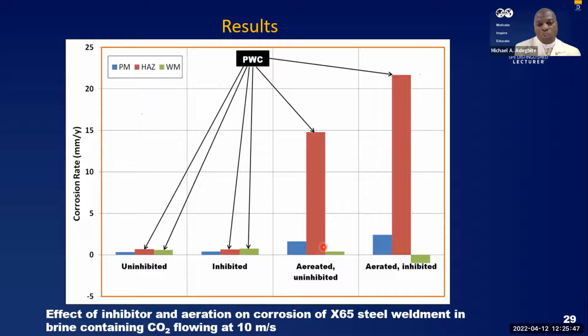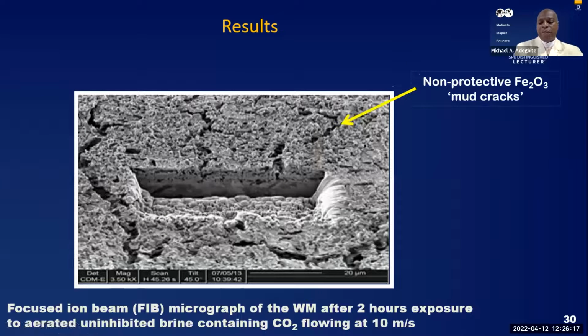And when that occurs, we have a spike in corrosion rate, and we can see that with aeration, either uninhibited or even when it's inhibited, even with inhibitor, corrosion is even higher because of admission or ingress of air into our system. So we have to keep eyes on air with respect to our systems. We must keep away air. We shouldn't allow that.